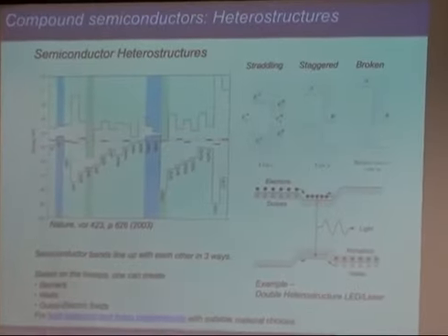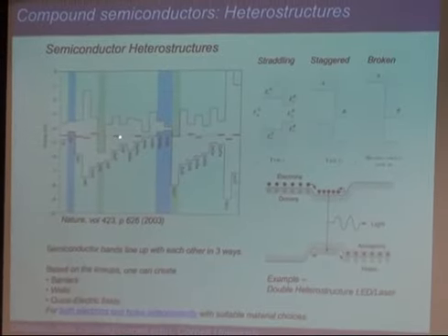What they were doing is computational studies of what the energy of the electron of a hydrogen atom would be if I introduce a hydrogen atom into the crystal. They find that for gallium phosphide, for example, it's somewhere in the middle of the gap compared to the band edges. For indium nitride, it is very deep in the conduction band. So they find different energies for different semiconductors, and when they align them all, assuming the hydrogen level is the same for all, it aligns the band offsets in a certain way, and they find the band offsets are pretty close to what we measure experimentally.